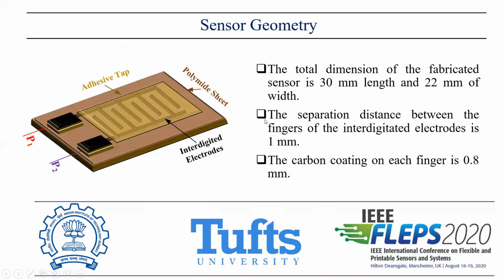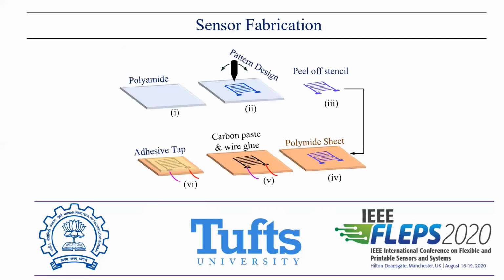We have done the fabrication using the screen printed method. Basically, a polyamide substrate was used for the sensor design, and this substrate is flexible in nature. The pattern was designed on the polyamide substrate to fabricate the interdigitated structure. The idea was to use the fringing field between those electrodes. This pattern was designed using laser cutting techniques. The electrodes were designed, and then a stencil was printed and placed onto the polymer substrate. And then we peel off the stencil, and only the pattern is printed on the polymer substrate. This is shown here.